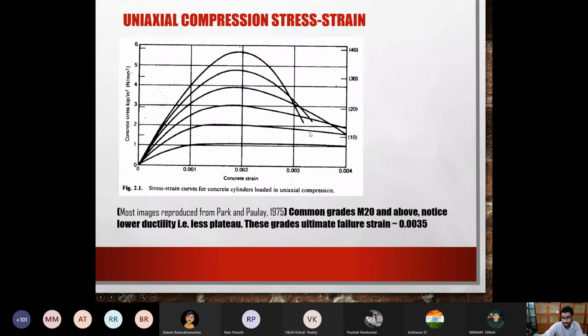Similarly, another thing you can find is that if you look at these two curves, they are ending at something after 0.003. This picture is taken from the ACI curve, the American standard. There they use the ultimate failure strain in flexural compression to be 0.003. In IS 456 we use 0.0035, which is the ultimate failure strain in flexural compression. So there's a difference between the strain you consider for axial compression and for flexural compression. The reason will come later.